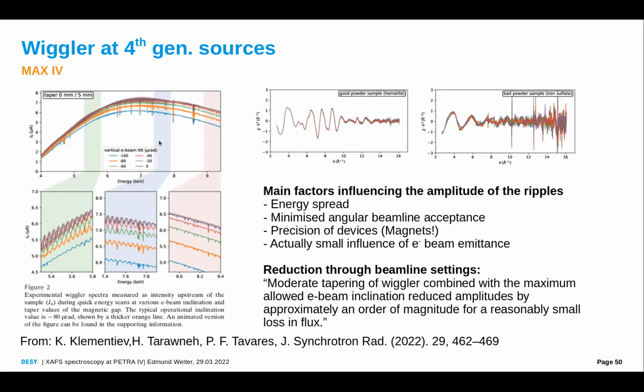And well, there are things you can do to smoothen this a bit. You can taper the wiggler. You can change the inclination of the electron beam in the wiggler slightly. There are things that have influence on the amplitude of these wiggles, but they are there. They seem to be manageable at MAX IV. It seems that the spectrum is sufficiently smooth to measure XAFS, but when you don't do anything, you really see differences in the spectra, or a lot of additional noise in the spectra, depending on the quality of the samples.